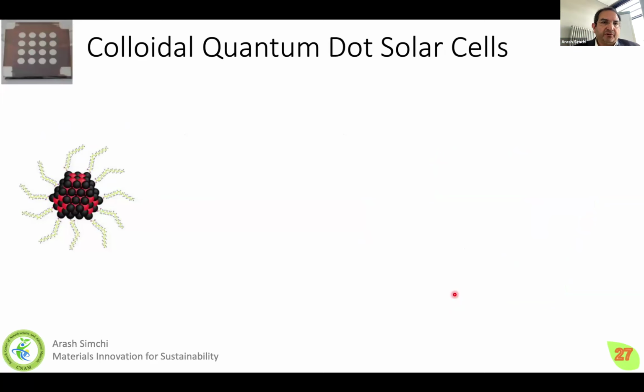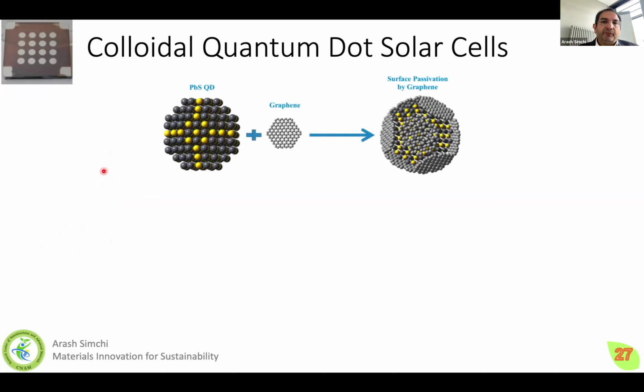about producing solar cells. I believe you know about quantum dot solar cells, which are relatively cheap and affordable. Usually the quantum dot has the problem that we have to passivate the surface with some organic ligands, which are not sustainable, and so on. We had an idea: instead of using ligands, we use graphene and passivate the dangling bonds of quantum dots in a way that we can make quantum dot solar cells. It seems to be a little bit of a weird idea.